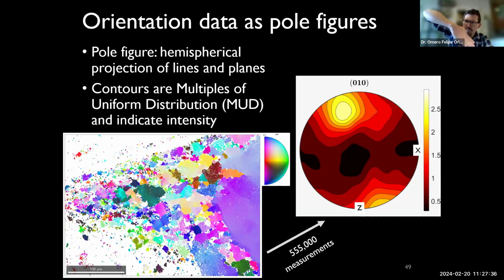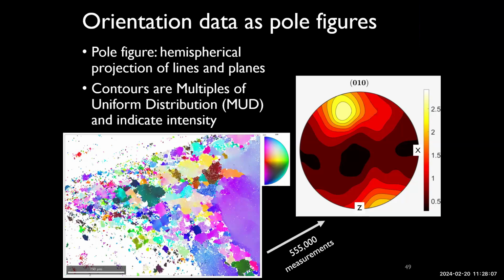And so it's showing you that the planes are all very strongly aligned because those are contours of occurrence density, basically, right? So a bunch of your 010 planes are all sharing a certain orientation, which is super cool. And it's exactly what you would expect for crystal plastic deformation, which is going to exploit the best slip systems that it possibly can for that particular mineral. They're all going to get on the same page and they're all going to end up oriented the same way, so that dislocations can proceed most easily.